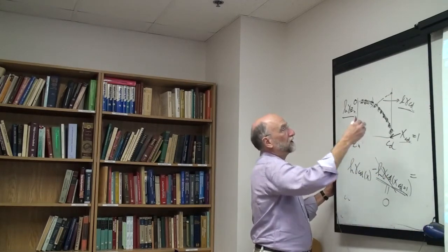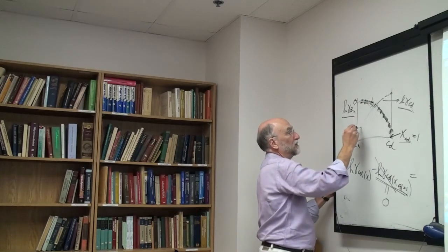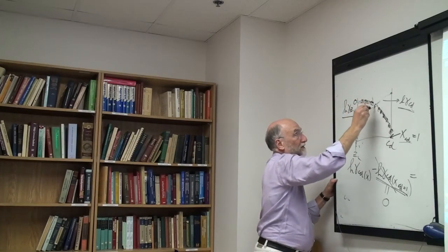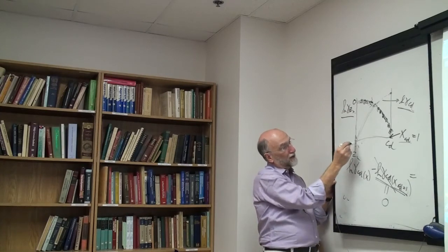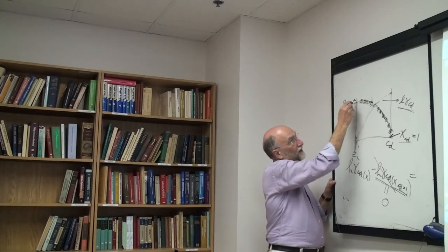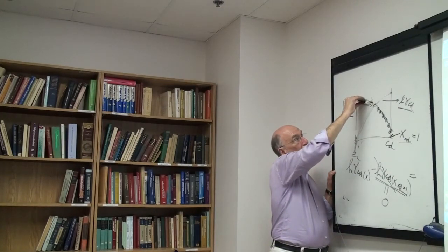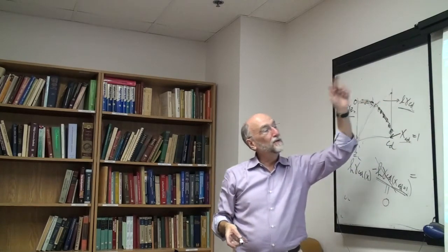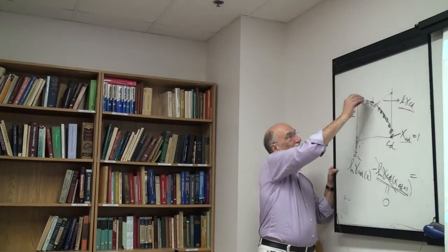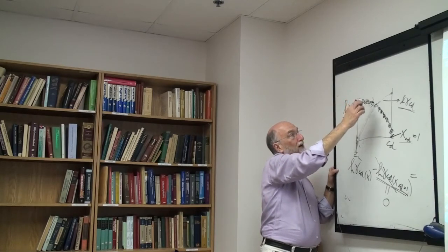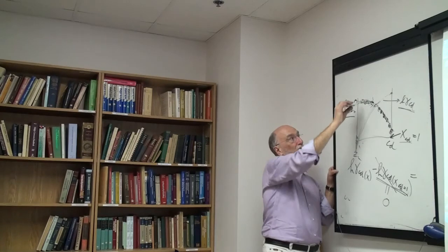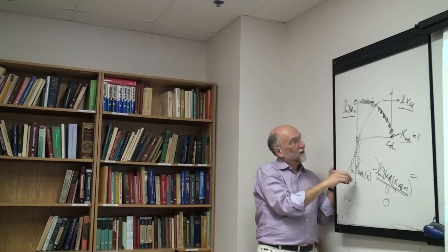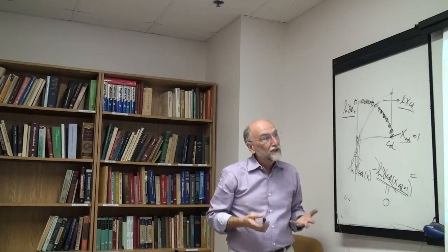So we do this whole thing, we do it kosher, and you end up with this expression. So this is your log gamma cadmium coming down to here. I've taken the zinc curve, this is my experimental point, I've integrated, and I get the log gamma cadmium. But the Gibbs-Duhem equation relates the slope here to the slope here. A very small change in the slope here can have a huge change in the slope here, because in the Gibbs-Duhem equation, the ratio x cadmium over x zinc goes to infinity. So these could be really quite accurate measurements of log gamma zinc, but since the slope is almost zero, very slight errors here can have a huge effect on this here. And that's something else that is masked when you're just leaving the equation.